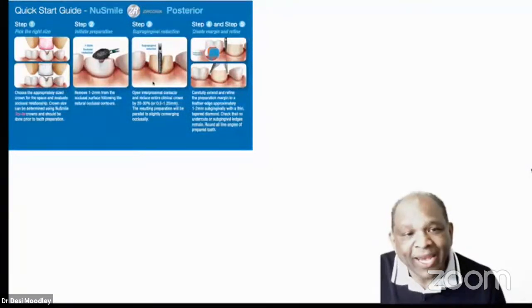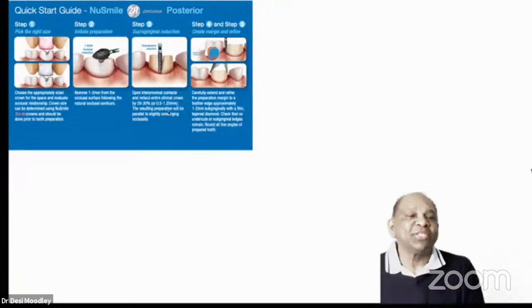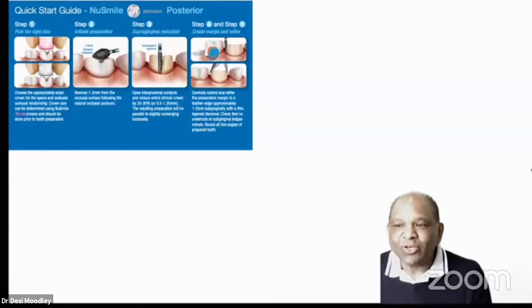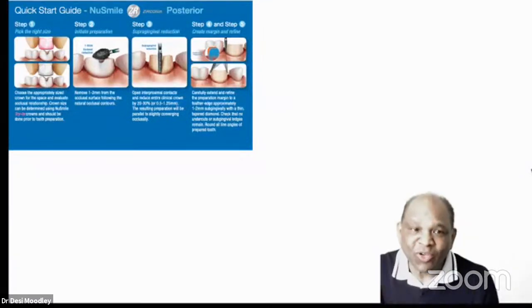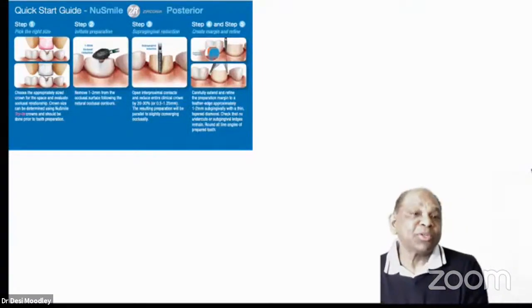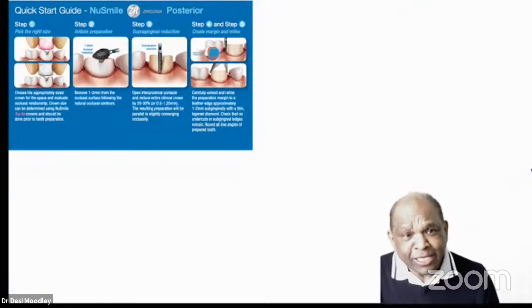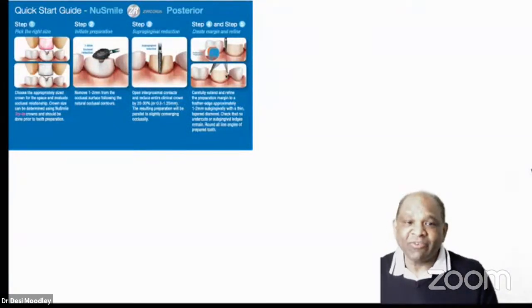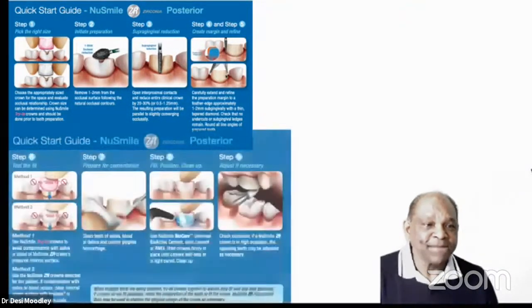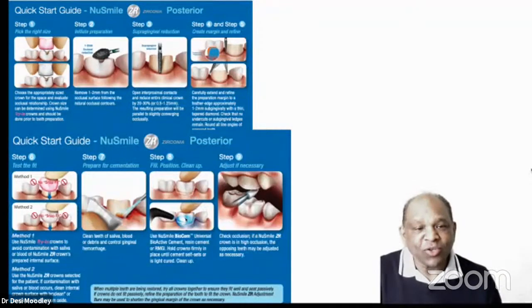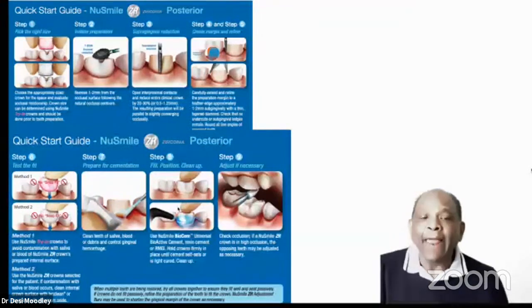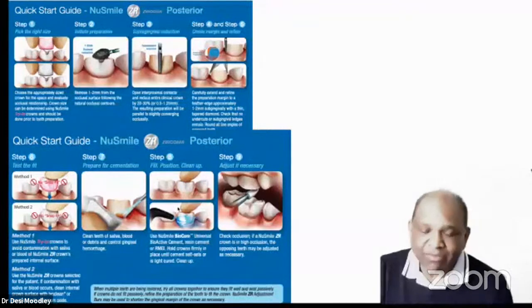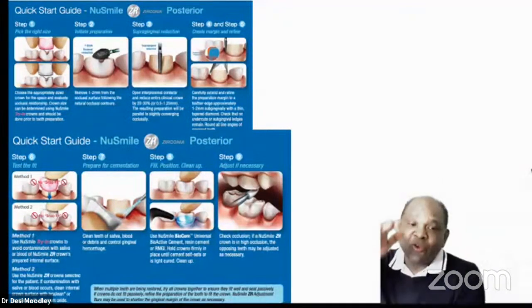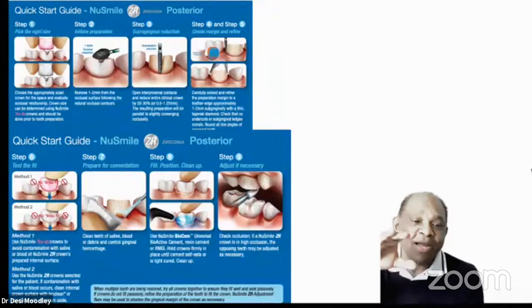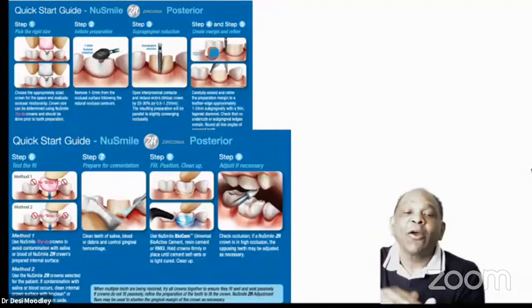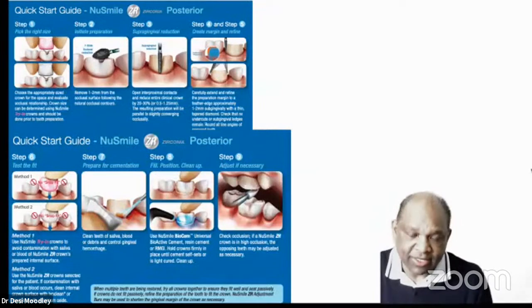You need to go at least 1 millimeter subgingivally. The reason you need to go subgingivally is because of the height you need to get down, otherwise you cannot adjust the occlusion. And we will talk about the occlusion now. Interproximally, there should be no undercuts whatsoever, because the crown will not slip in. Once you've got that, you need to go in subgingivally, and the reason for that is, if you do not go subgingivally, the height of the crown will be too long. So it's going to cause a hyperocclusion.